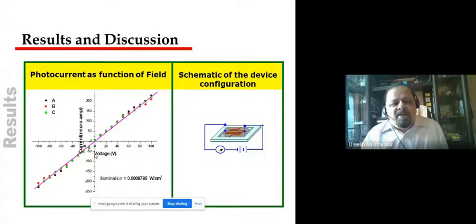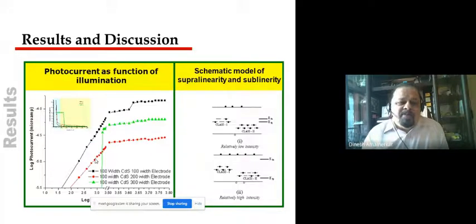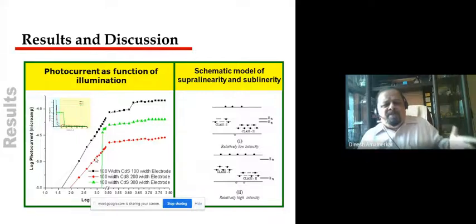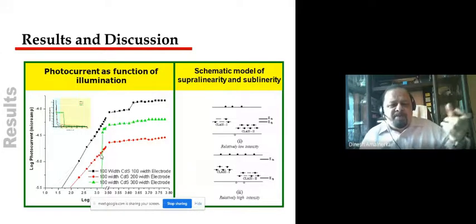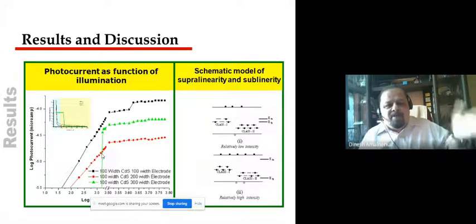What is the guarantee that the ohmic contacts have been formed? This is the first test. If you see both the dark current as a function of the field, and the photocurrent as a function of field, we get a straight line, which indicates the ohmic nature of silver for this particular cadmium sulfide. Then there is a typical behavior, sublinear, linear, or superlinear, of photocurrent versus intensity of excitation. This is a typical behavior pattern depending upon the exposure level and also the concentration of copper in cadmium sulfide. I'm not going to talk much about that.